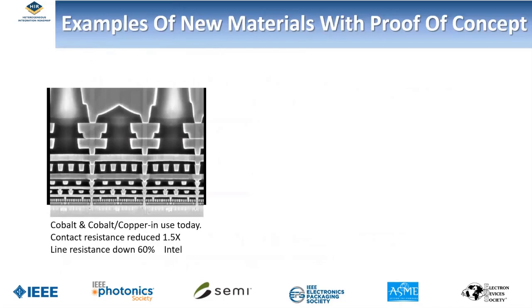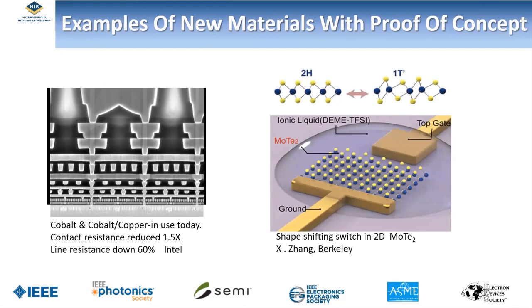Here are examples of proof of concept. Using cobalt, line resistance went down by 60% and contact resistance by 1.5 reduction. And in the new device types, we have a shape-shifting material where we can use a 2D moly telluride, and by applying voltage, cause some of those structures to rise higher above the plane. And so it's very low energy and very high density, but still developmental. Next slide.